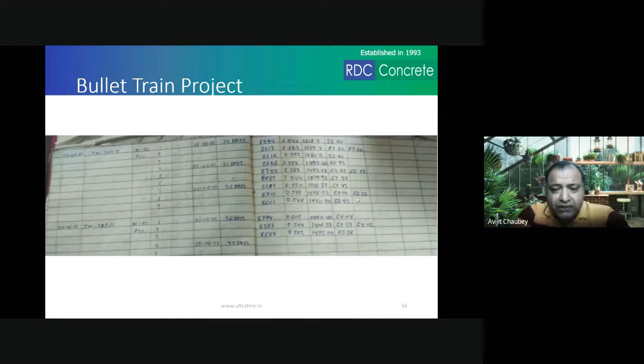They were facing a lot of challenges in terms of bug holes in the sections that they were casting for M50 grade concrete for the bullet train, the girders that they were casting. So they used to get a lot of cracks, also because it was a mass concrete, and microsilica being very sticky, because it is a densified material. You require a lot of admixture to disperse it, and even after you have dispersed, the mix remains sticky, and also because it is much finer as compared to ultrafine. So these materials have been able to give much higher strength with better workability and pumpability.